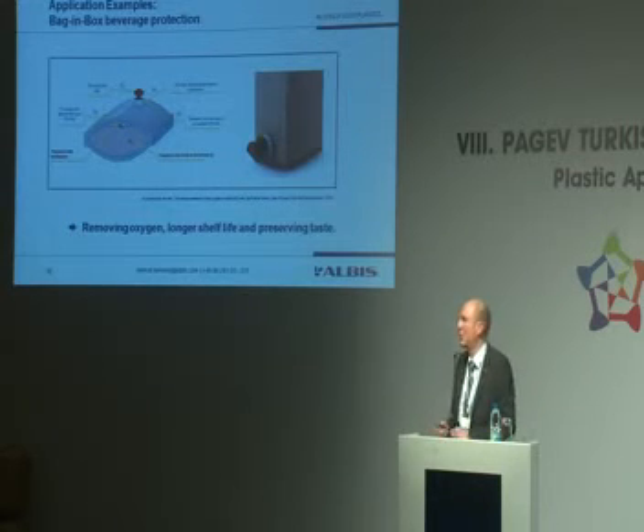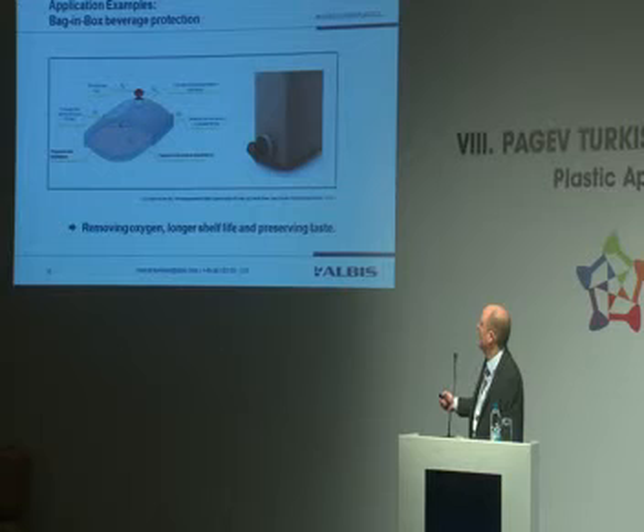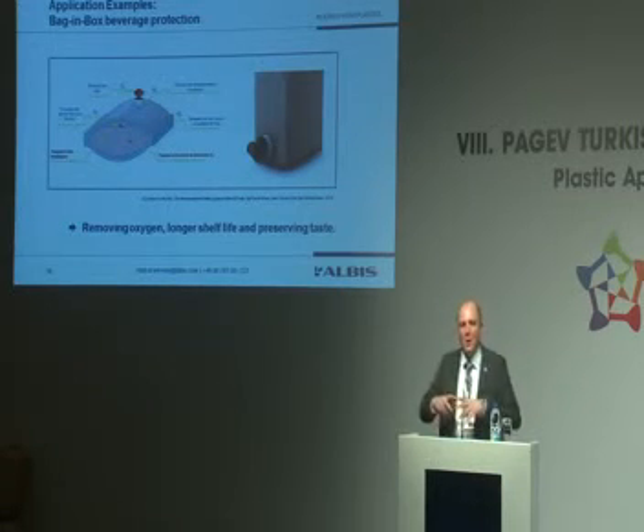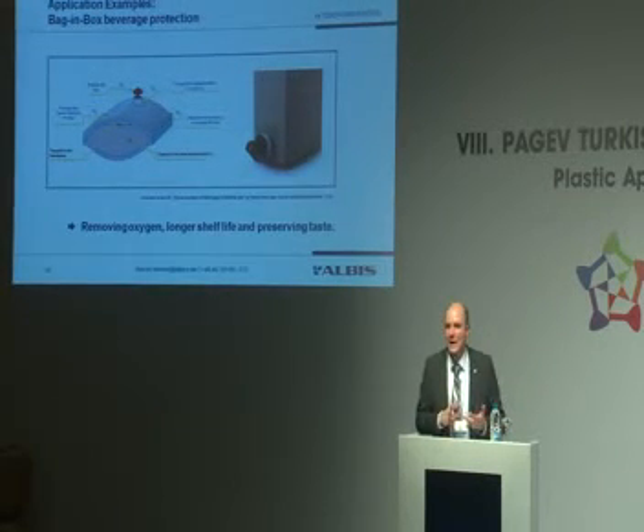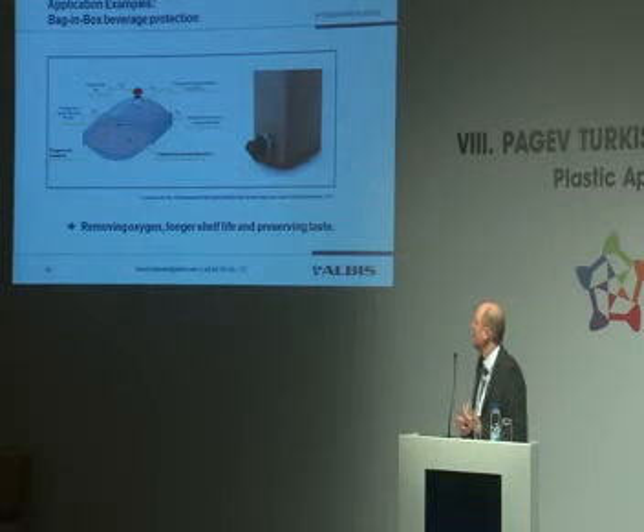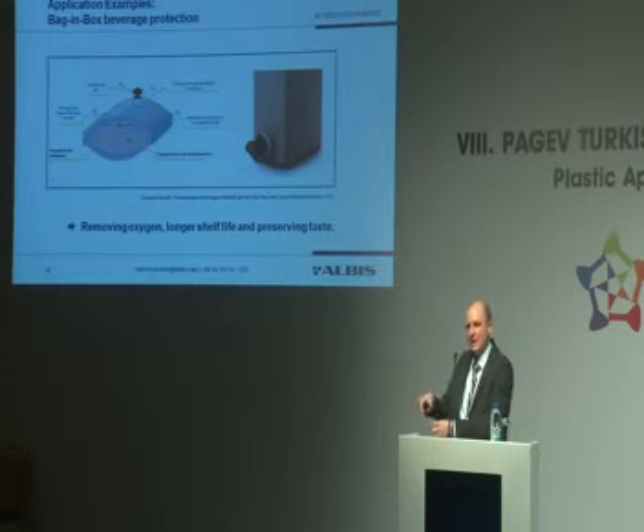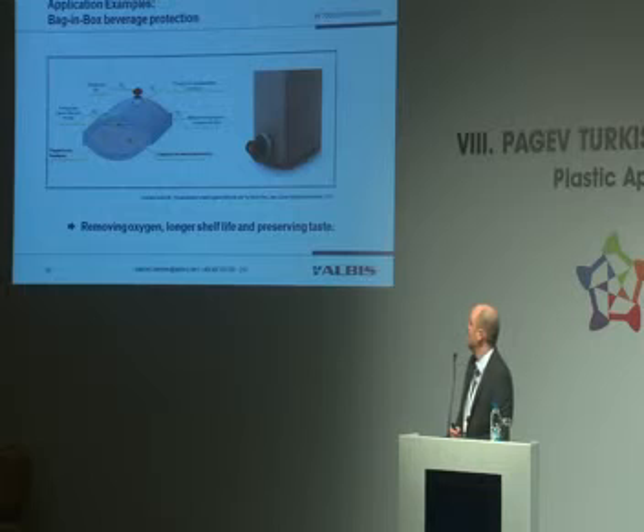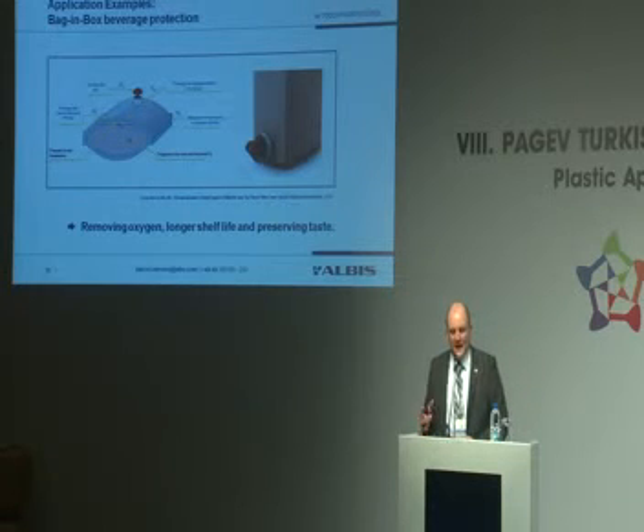A little bit of an outlook, what can be done next? For us, a very promising project is bag in box, so a pouch basically filled with a beverage, with a drink. This can be wine, this can be beer, this can be apple juice, can be also tomato juice. And then this pouch is put into a cardboard box and you can put it in your fridge and tap glass by glass, portion by portion. And this setup of application is very sensitive to oxygen ingress. You have oxygen in the wine, in the headspace. It can come in through the welding lines, through the tap, so a lot of possible oxygen ingress. And there you really have a high opportunity, if you apply an oxygen scavenger, to make this application work better.